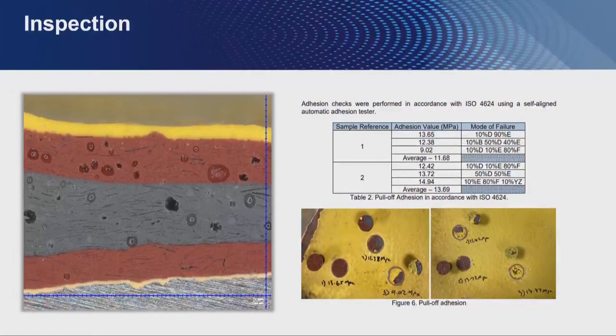And the adhesion failure was actually not with the steel, but it was with the top and the mid coat. So from an adhesion perspective, the coating system, the scheme, held together in some of the harshest conditions for 40 years, applied once, no maintenance, no touch-ups, just as is.